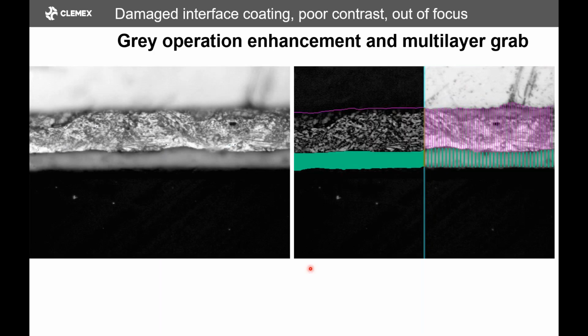Here's another example of a challenge. We're looking at this coating at fairly high magnification, and the issue is that this is out of focus here, and also this area here is difficult to pick up because it merges with this one. So we use a multi-layer grab, and we can see that all the layers are pretty much in focus now. So everything is easier to measure.